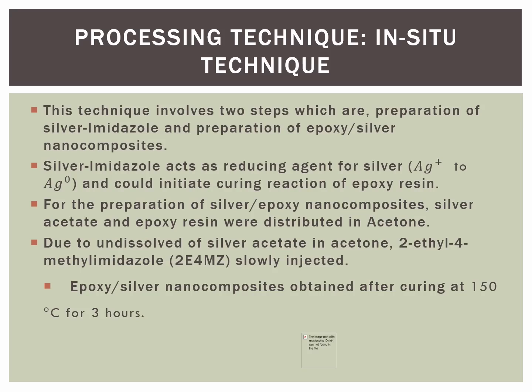a reducing agent for silver. Imidazole was immediately released from complex and could initiate the curing reaction of epoxy resin. The silver acetate was added to CH2Cl2 solution of 2E4MZ, and the mixture was stirred for 2 hours until all silver acetate solid disappeared, and the solvent was condensed to approximately 2 ml. Then ether was added to give white precipitates, and the solid was filtered off and collected. The product was obtained as a white solid after recrystallization by dichloromethane diethyl ether with a yield of 85%.